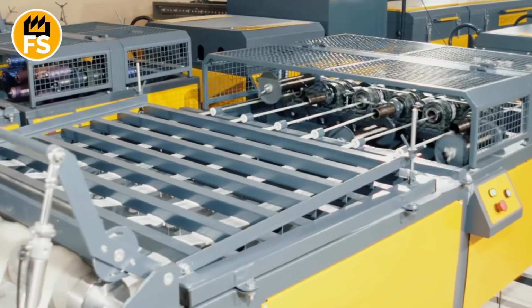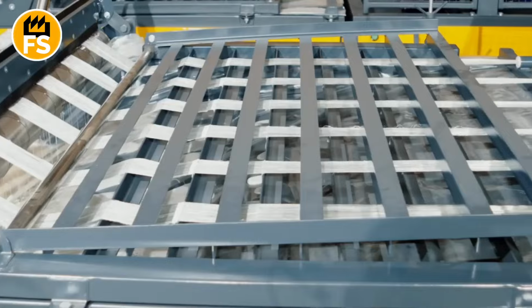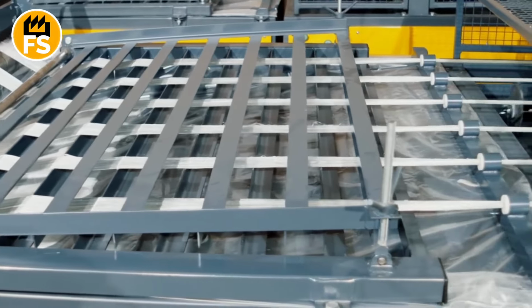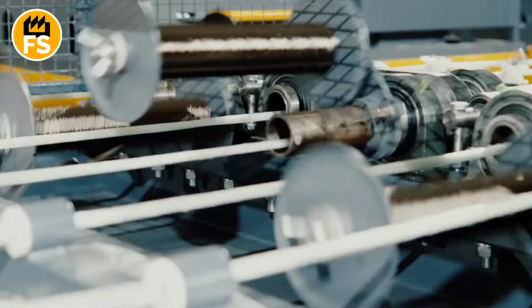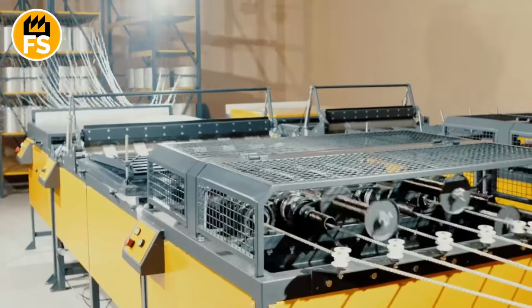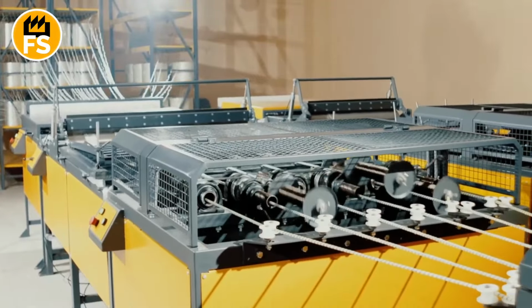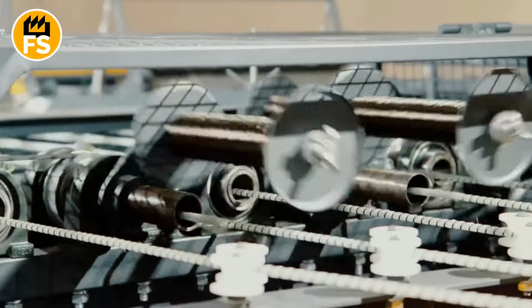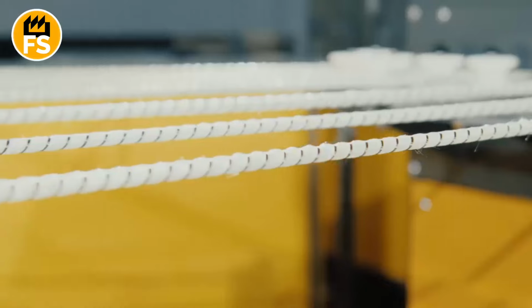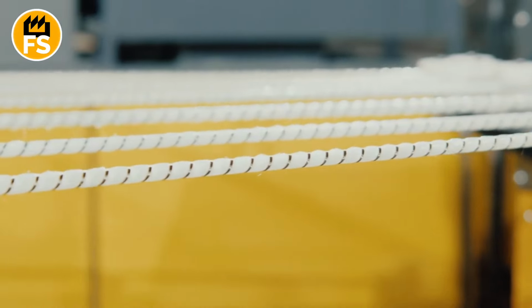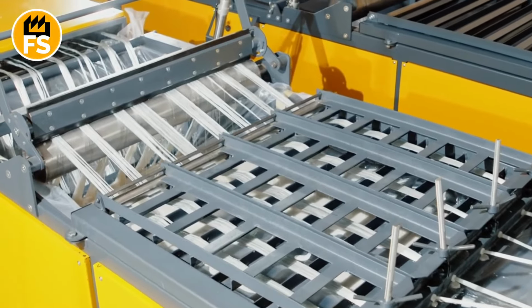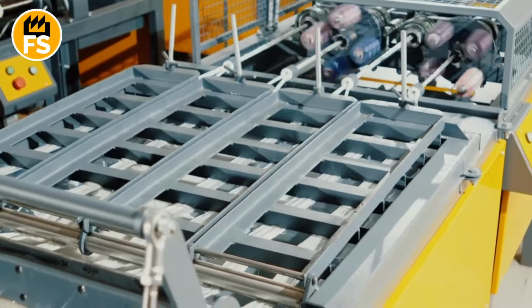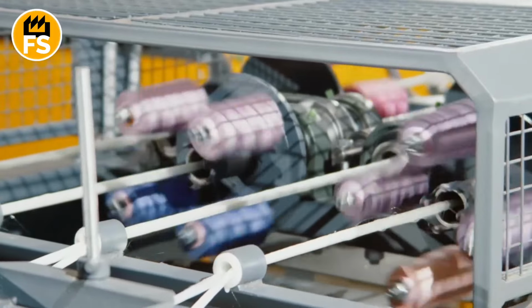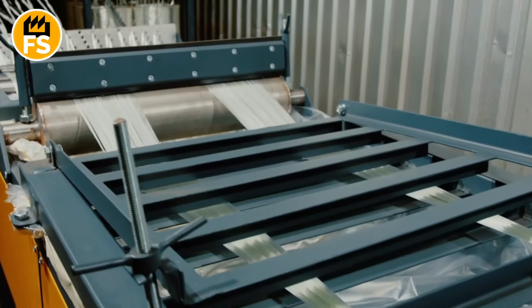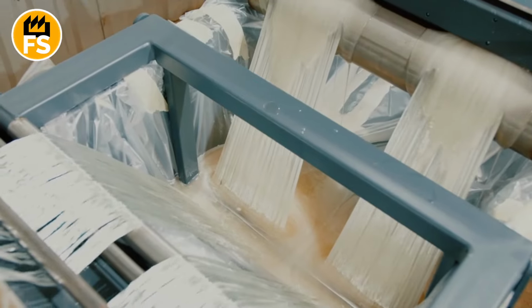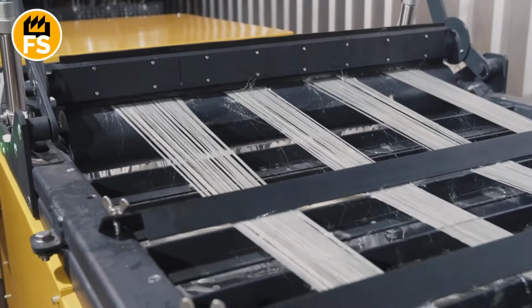The soaked bundle, heavy with sticky resin, comes out of the bath and heads to the point of its birth, the forming die. This is the heart of the whole process. Imagine a thick steel plate with a perfectly round, polished hole, the diameter of which exactly corresponds to the diameter of the future rod. The die is heated to a certain temperature. When the wet bundle is drawn into this hole, several things happen at once. First, the die, like a press, squeezes out all the excess resin, leaving only the necessary amount.